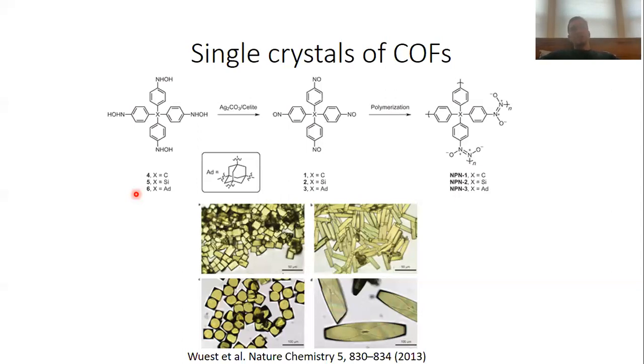So this is often the method how the X-ray diffraction patterns of covalent organic frameworks are being analyzed. Because of the relatively high complexity of the covalent organic frameworks, the direct methods to determine the location of the atoms in the unit cell is not possible, okay?